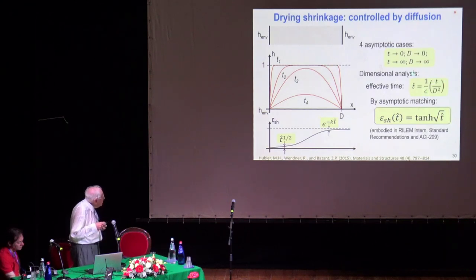This is diffusivity, effective diffusivity. And these are the asymptotic cases on the left side, right side, which are known. This must be exponential, this must be a power law. And this formula, which is plotted here, gives agreement with both asymptotes. This is now used in the B3 model and in the ACI guidelines also.